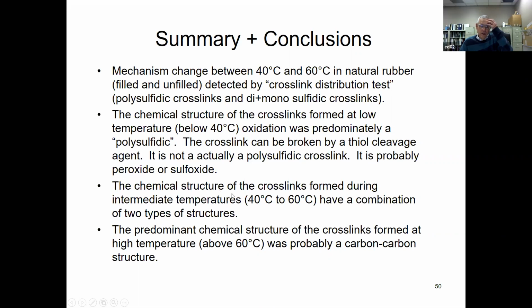The chemical structure of the crosslinks formed at intermediate temperature, 40 to 60 degrees, is a combination of two types of structures. The predominant chemical structure of the crosslinks formed at high temperature, above 60 degrees, is probably a carbon-carbon crosslink structure.